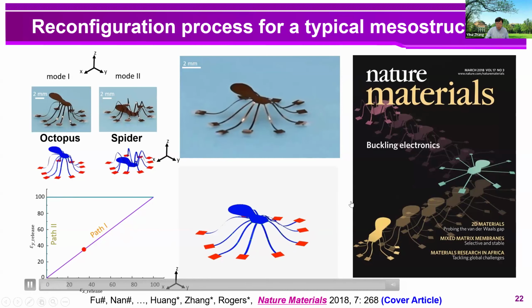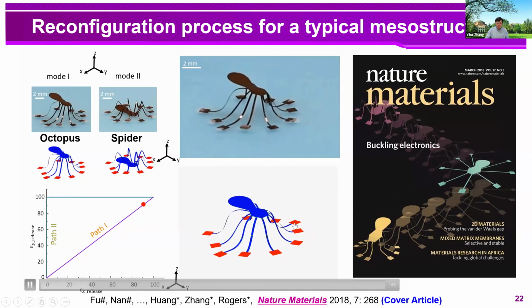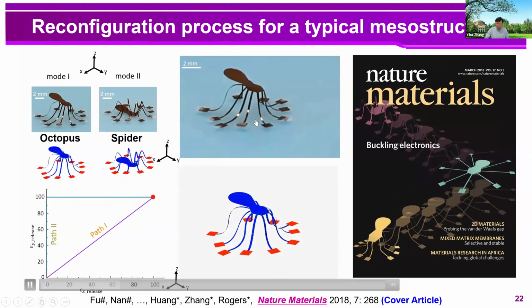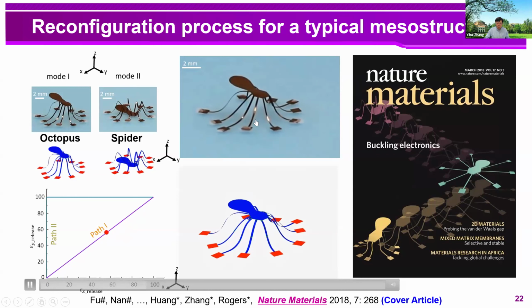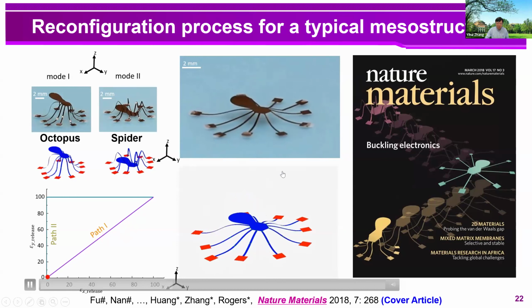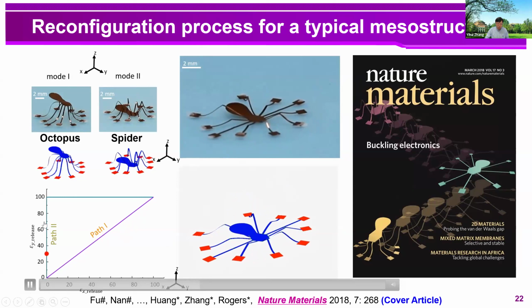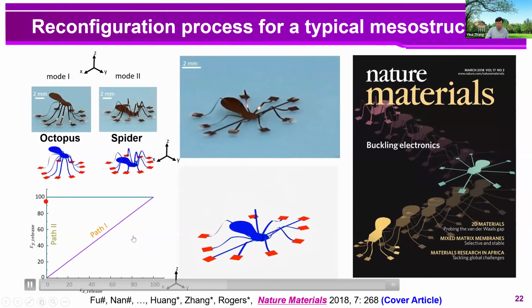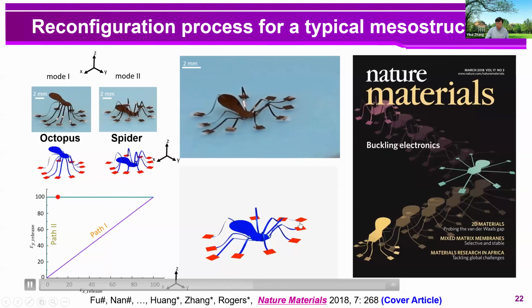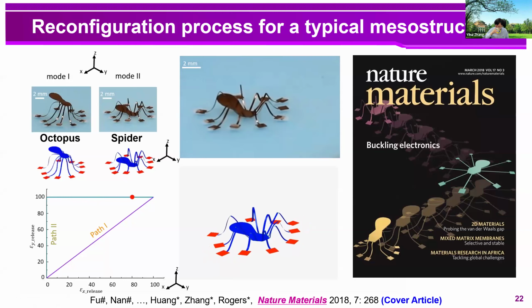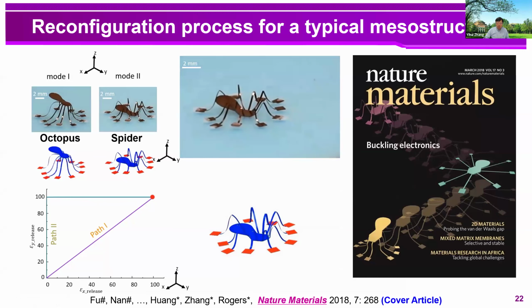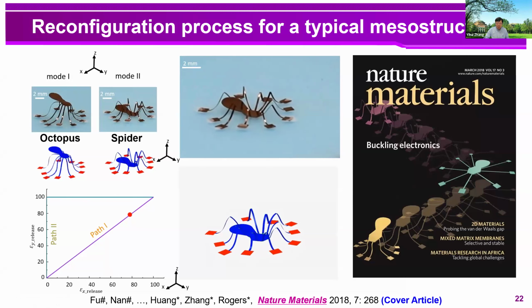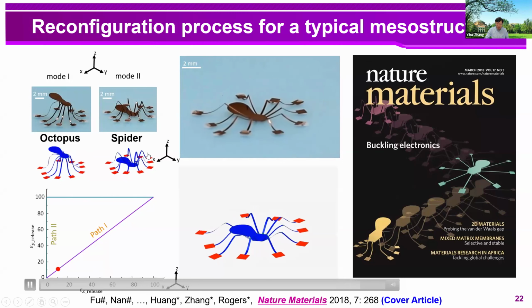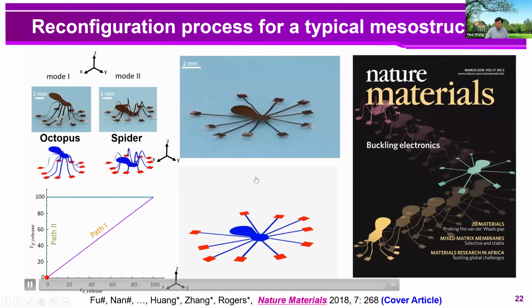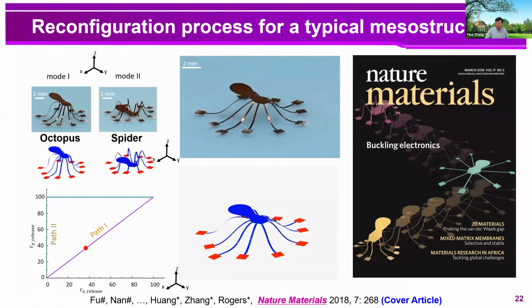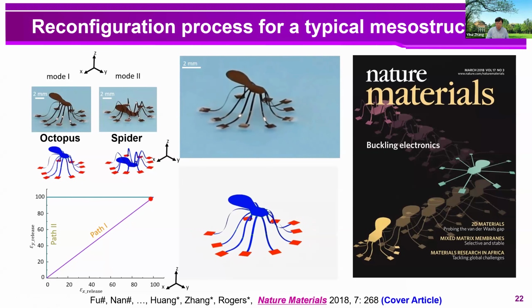If you release the biaxial pre-strain simultaneously from two directions, the 2D structure will be assembled into this octopus 3D structure. And if you stretch the substrate again, the structure will go flat. And then if you do sequential release by releasing y directional strain first and x second, the structure will be reshaped into a spider. And actually, this reconfiguration process can be done thousands of times, meaning that this octopus can be reshaped to this spider thousands of times, even if it's made of metal, because we can use mechanics design to control the value of the maximum strain in the 3D structure during the process.